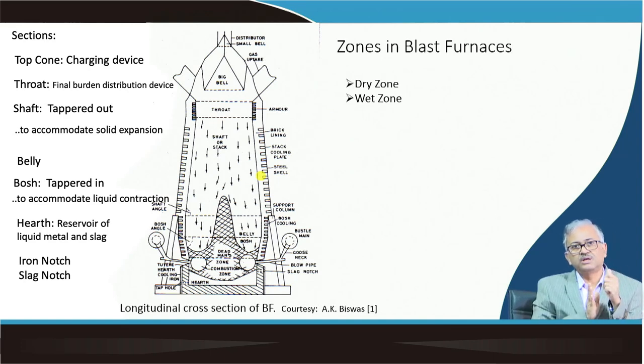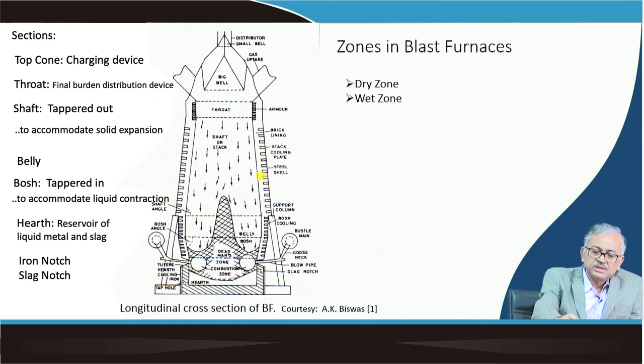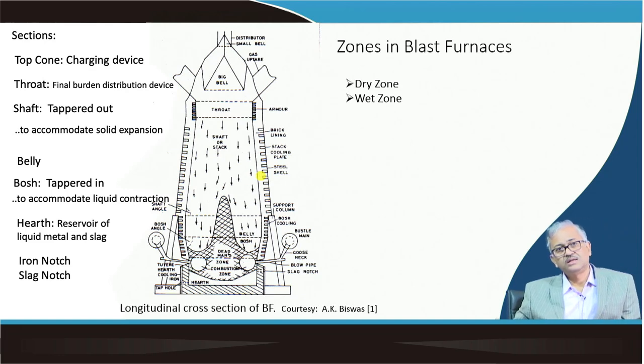In the wet zone, gas moves up against the liquid, and in the dry zone, the gas moves up against the solid. So here basically there is a gas-solid reaction, and in the wet zone there is a liquid-gas interaction, and that is also very important. In both the regions you should have sufficient permeability such that the gas can pass through. Okay,